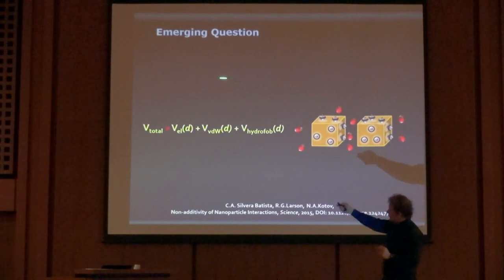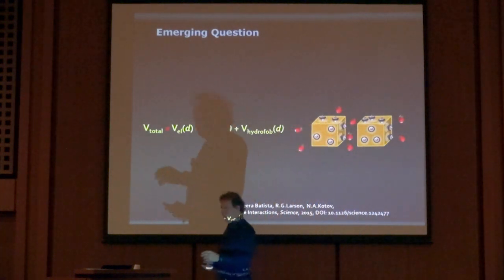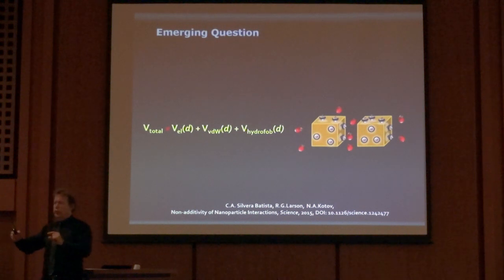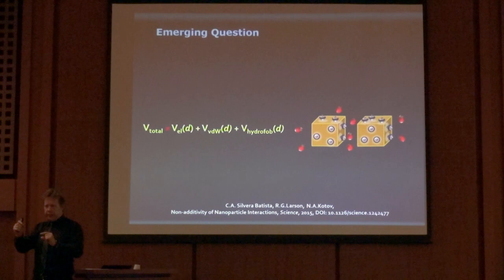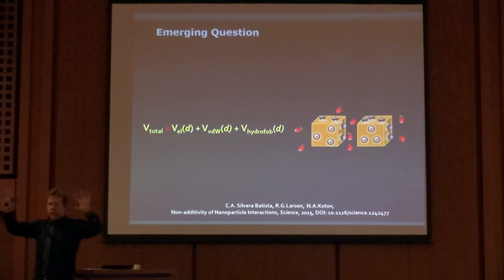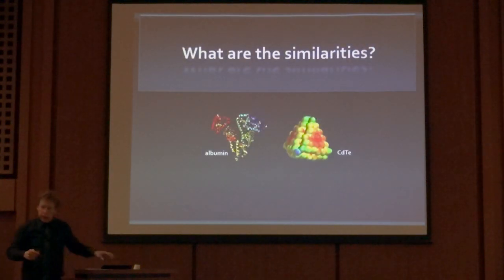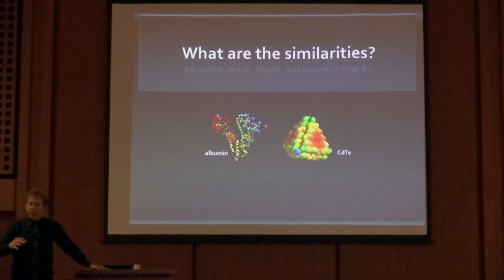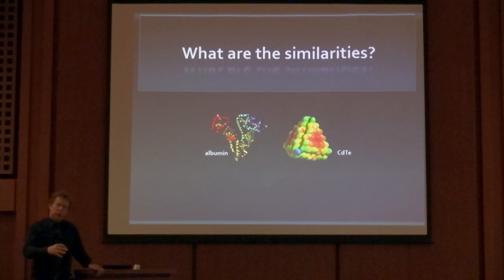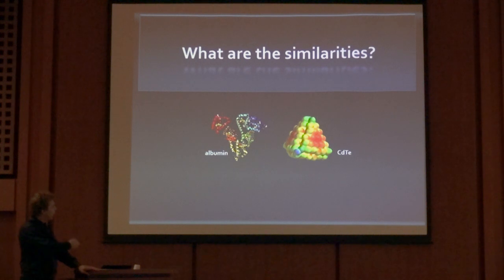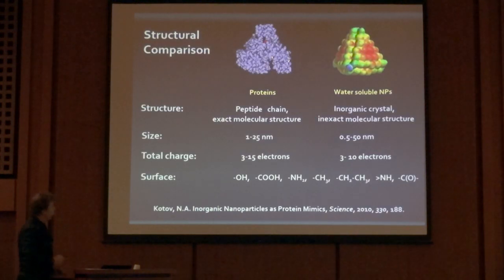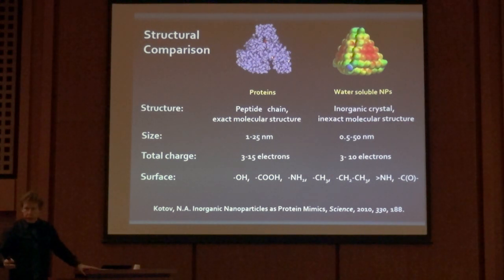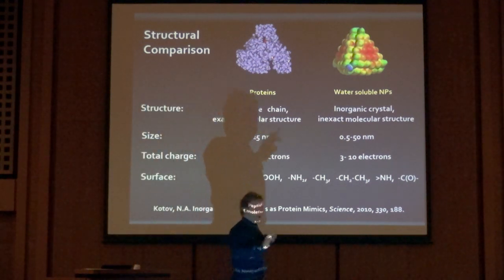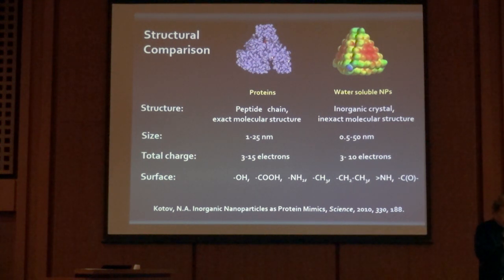At this point, even just accepting the fact that these are non-additive systems gives us a certain toolbox for how to engineer them. And this toolbox comes not from mathematics, the toolbox comes from biology, because the interaction of biological systems is known to be non-additive for a very long time. And this brings me to the point of comparison where the nanoparticle assemblies and nanoparticles themselves are similar to the organic and biological systems. If we compare the parameters of nanoparticles with those of globular proteins, we can see that the size, the charge, the surface chemistry, in particular for water-soluble structures, are almost exactly matching each other. And this is not an accident.